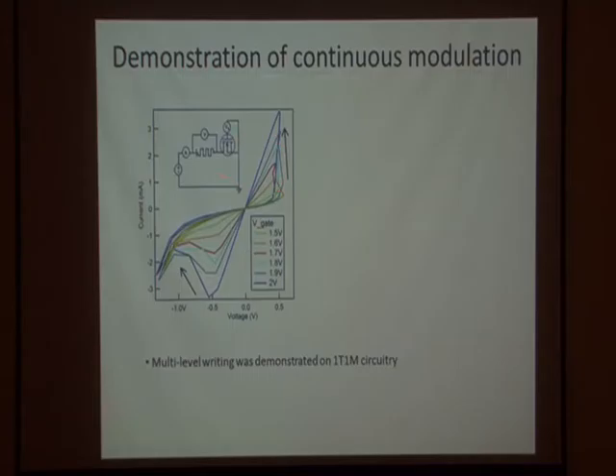What we do is the so-called current compliance, but the way that we implemented that was not with a $100,000 piece of equipment like a B1500 Agilent. What we did was something much simpler. We got an FET, and we controlled the current through the device with this FET. That's it, it's as simple as that. Depending on the gate voltage, we can control the current that flows through the device. So this technique is very good for controlling the channel size, if you will, and the composition.